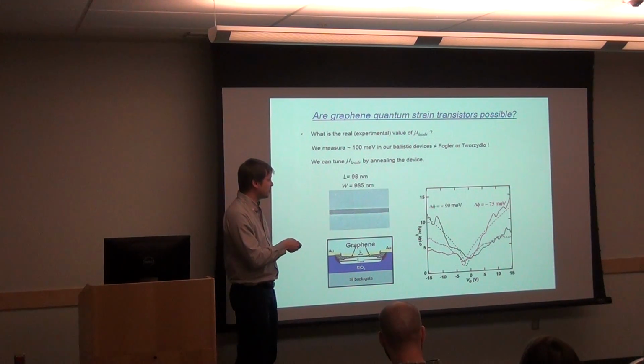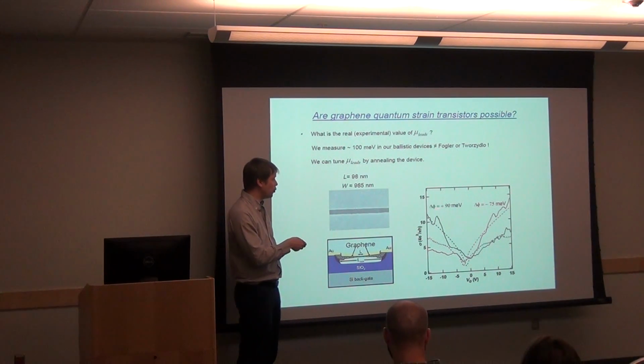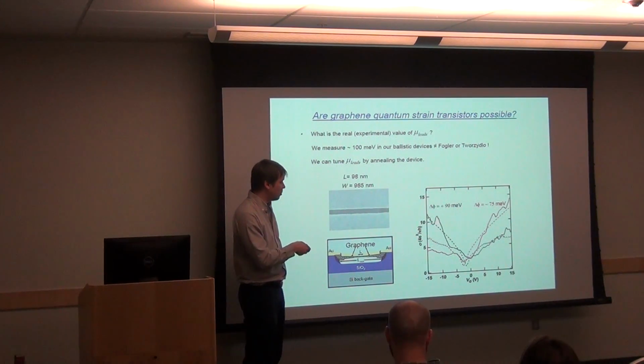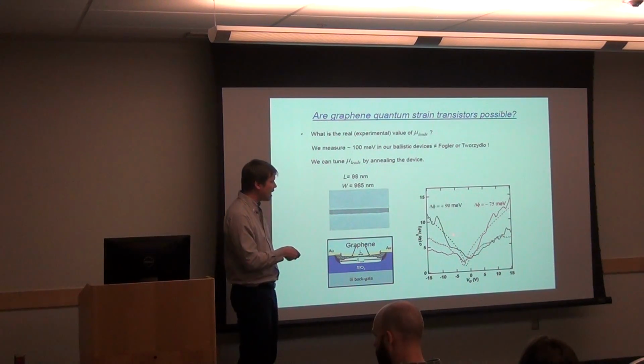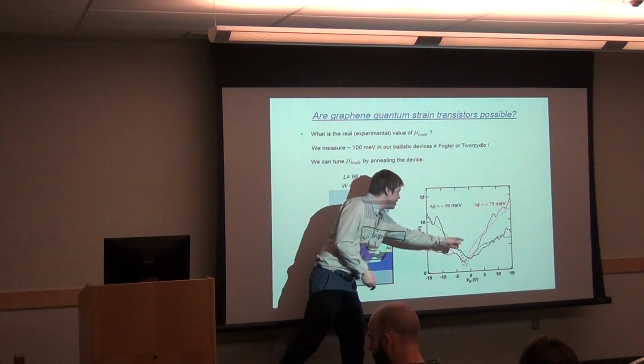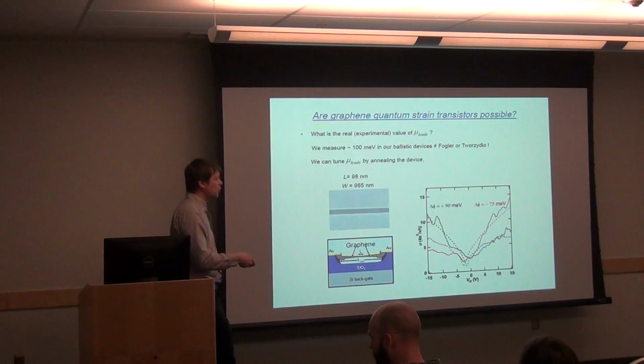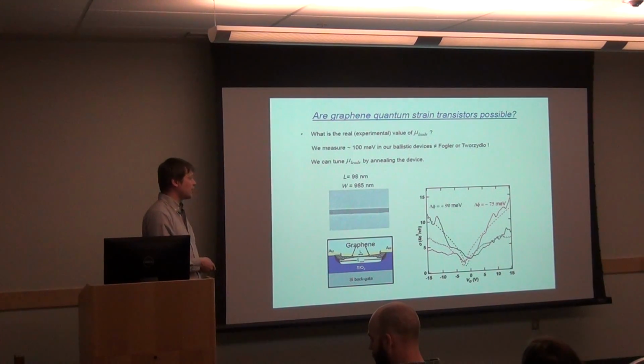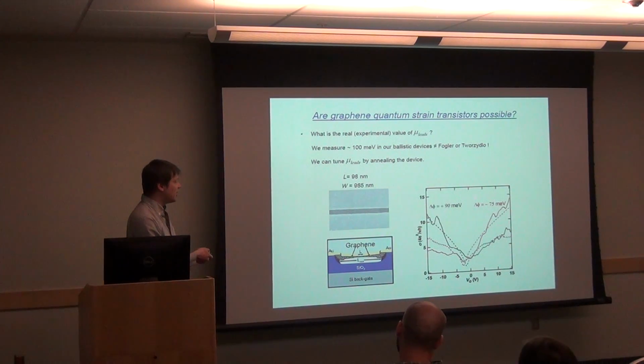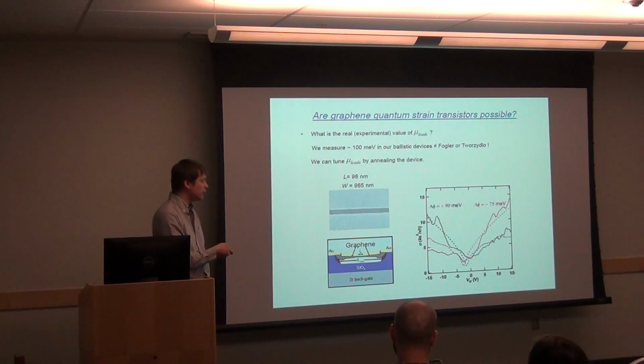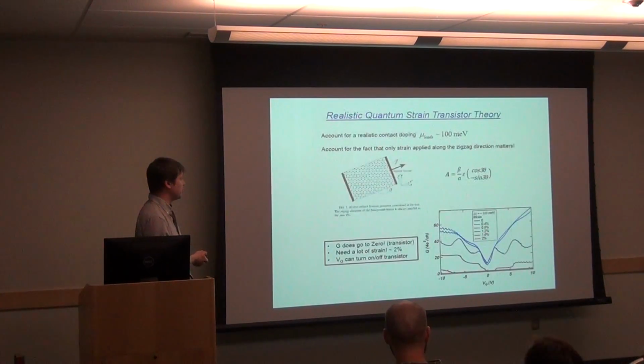This is negative, basically electron doping, and this is positive for hole doping, at plus 90, then we get the black curves. So there's very good matching, and you can see that there's a left to right asymmetry that's flipping, depending on whether you're doping with holes or electrons. And it makes sense because the p-n barrier interface is different for the two cases. The point is that this chemical potential in the leads is now of the order of 100 millielectron volt, and it's also something we can tune.